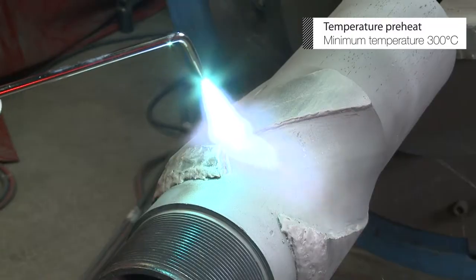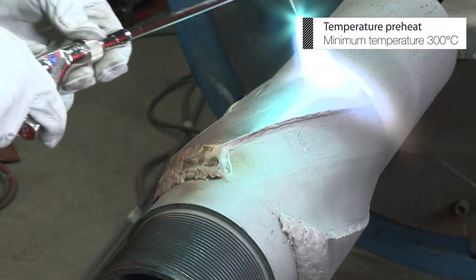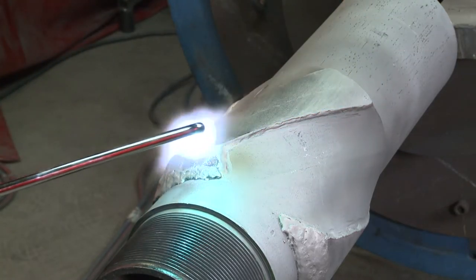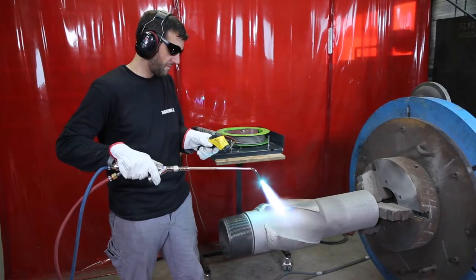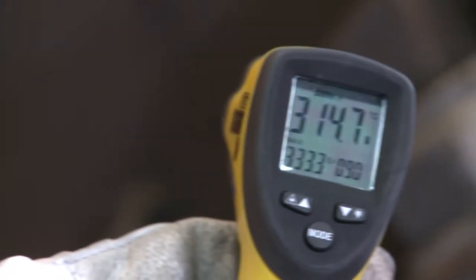Due to the size of the part, you may need to preheat several times to maintain 300°C during the welding process. This is a critical step. You can always use a temperature probe or a temperature pen to check the proper temperature.